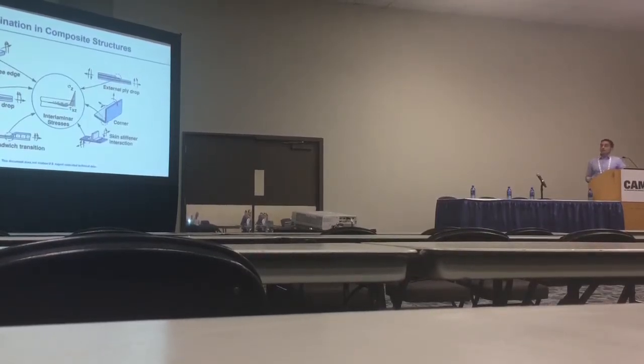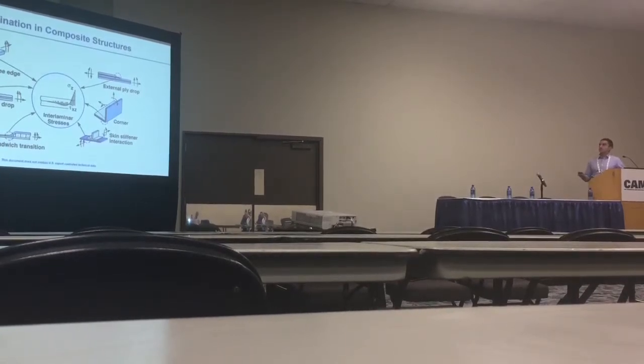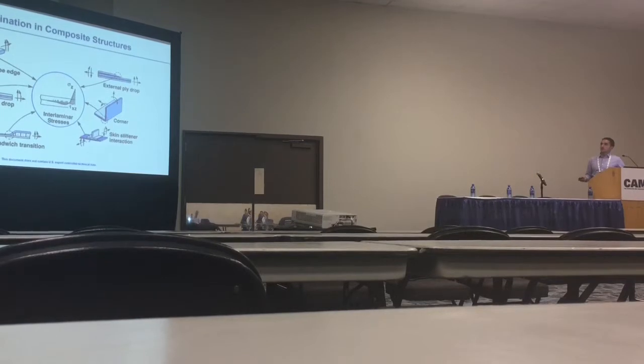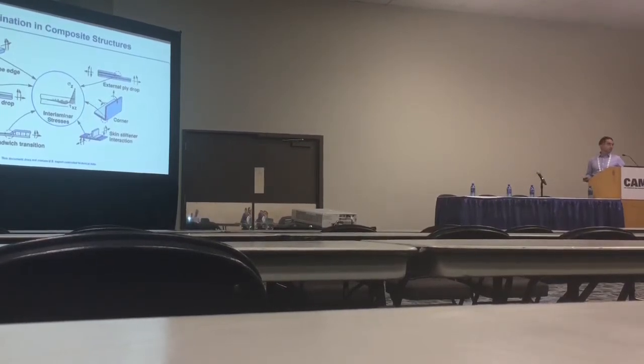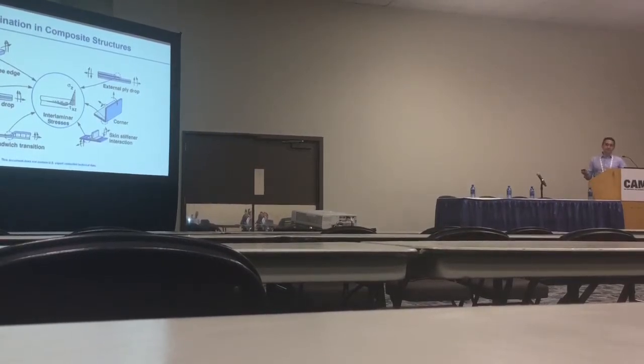To do that, what you need to do is understand your structural behavior, okay? As a lot of you guys know already, composites are pretty weak out of plane. The out of plane behavior of composites is pretty weak, and it's generated through a lot of these reasons, right? If you have a straight edge, you have stress concentrations at that point, the change in geometry, the change in stiffness, the asymmetry, and so on. That's a pretty big problem within composites, and a lot of people have been solving it through different manners.